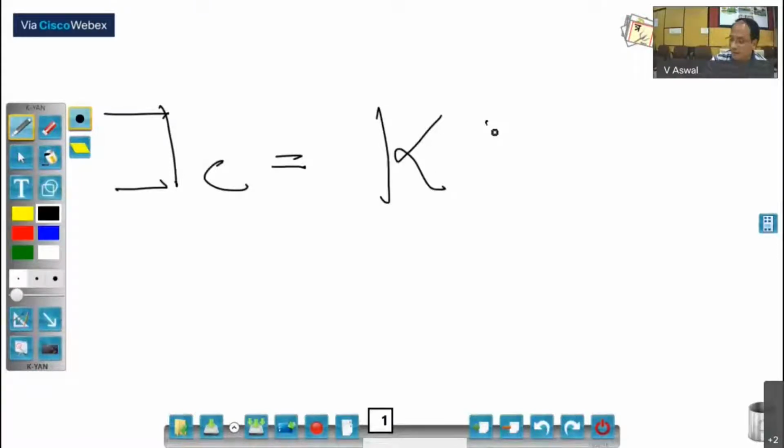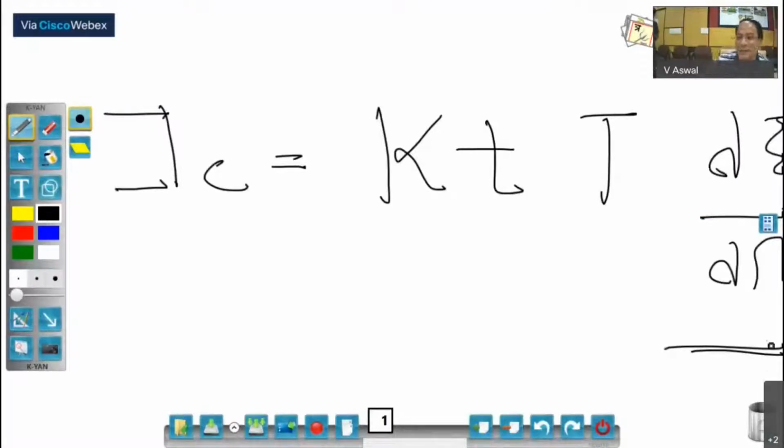Okay, so what is also important is whatever corrected intensity you get, you have to normalize it to a property of the sample. And how do you do that? Then you have this corrected intensity equal to some constant, then thickness, then transmission, and then the last term is the property of the sample, which is the differential scattering cross section per unit volume. So now you know everything actually. So you know your corrected scattering intensity, then thickness, transmission, and this is what you would like to have, the normalized scattering intensity.